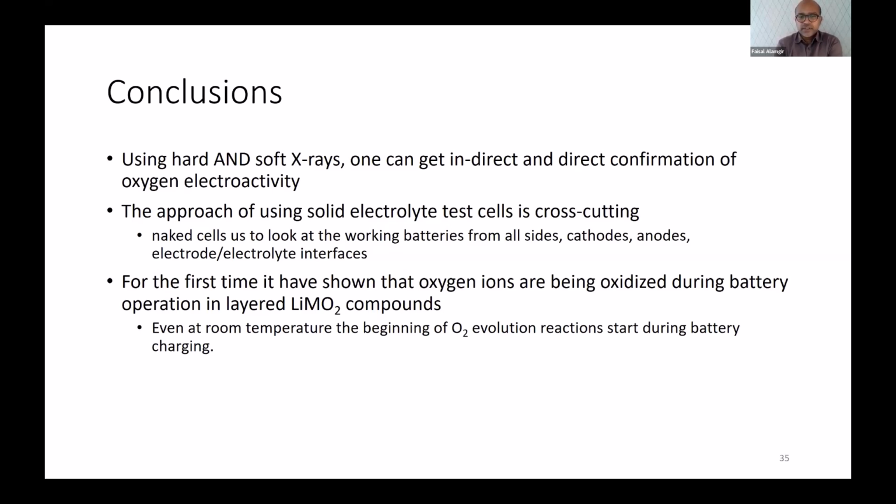And I think this was the first time that an in-situ or operando battery showed oxygen activity. I will stand by that unless somebody corrects me. But as I said, others had conjectured, in fact, Jack's paper that I referenced was referencing another paper prior to that, where there were already ideas of oxygen electron holes and oxygen sites, and there were some ex-situ experiments already done to confirm some of these ideas, and also some theory work. But as I said, the operando experiments helped to confirm a lot of these initial ideas. So I'll stop there.